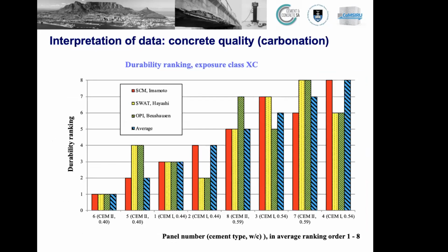What you see here is different methods used to design concrete for exposure class XC, which is carbonation-induced reinforcement corrosion. What is nice to see here is that, in principle, with a bit of scatter, all these methods can agree on the principal quality of the concrete. So I would take this as a positive sign to say, worldwide, the developments have led to test methods that give us a similar picture of the quality of the concrete. So this confirms that we can use these test methods in the design and quality control of our structures.